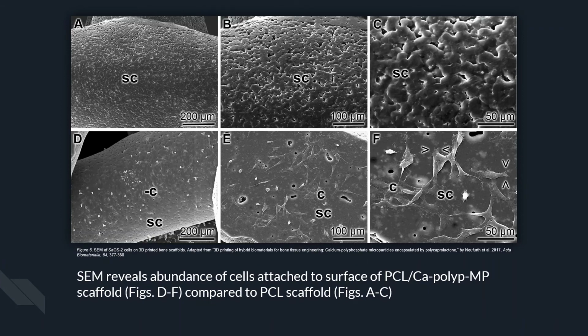Scanning electron microscopy, or SEM, was used for closer inspection of cell density and morphology. The seeded scaffolds were assessed after 3 days of cell incubation. No cells were discernible for the PCl scaffold, shown in panels A through C. In contrast, the PCl calcium poly-P scaffold showed abundant cell growth as seen in panels D through F. Living cells are highlighted with a black C for the PCl calcium poly-P scaffold.